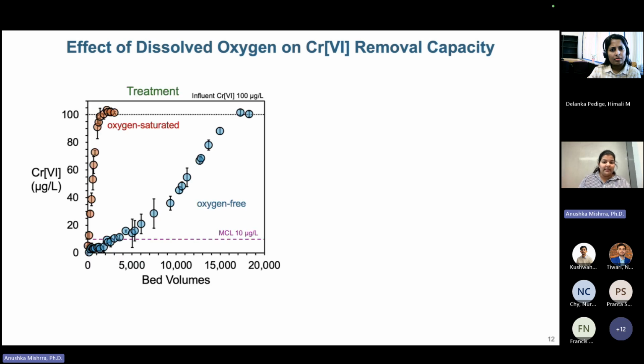To do that, we ran our columns in an anaerobic chamber so we could control the dissolved oxygen in the water. We ran water that was completely deaerated and then looked at the chromium. What you're looking at now is my previous data, shown in the orange circles, which stops at 1,000 bed volumes. We are also looking at an oxygen-free system, with non-detectable amounts of dissolved oxygen in the water, and this significantly increases the treatment capacity for the material—it's gone 17 times higher than we would see in a normal system.